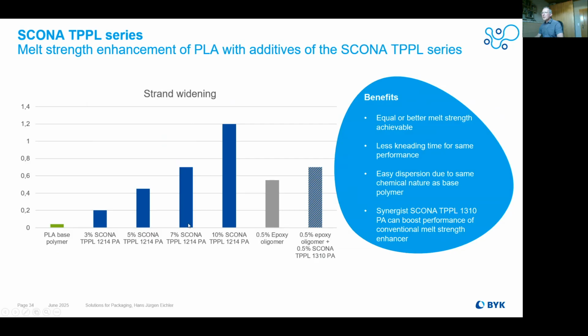If we look here into these figures which are showing the strand widening, you may wonder why we place on here strand widening. The reason for it is the strand widening is correlating with the melt strength. So means if the strand widening is getting big, the melt strength is also getting big. So we made these figures here with our MFR equipment, means we measure the strands which are coming out of the MFR. And like I said, if the strand is getting wider, it means the melt strength is still improved.